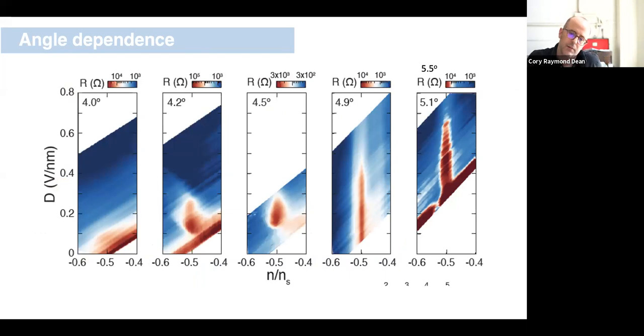Great, so that's a detailed discussion of a measurement for a single twist angle device. We can repeat this measurement for all the different twist angle devices that we made, again, spanning from about 4 degrees to about 5.1 degrees. What limits this range is that at small angle, all of the interesting densities get pushed into the disorder limit of the device and we can't resolve anything. And at high twist angle, things get pushed to too high of a density that we can't access by gating.